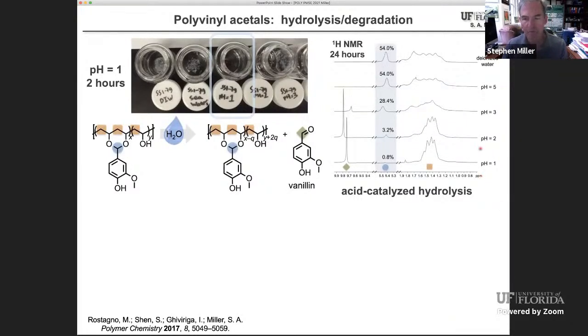Not surprisingly, if we throw them into fairly acidic aqueous conditions, we do see hydrolysis. If the pH is 1 or 2, you get essentially complete hydrolysis in the course of a day. At pH 3, hydrolysis is incomplete, but nonetheless measurable. But at pH 5 or pH 7, we really don't see any substantial hydrolysis over the course of a day. And we've done some longer experiments, but the polymer is pretty resistant to neutral water conditions, be it deionized water or, for example, seawater, which we also use as a medium for our degradation studies.